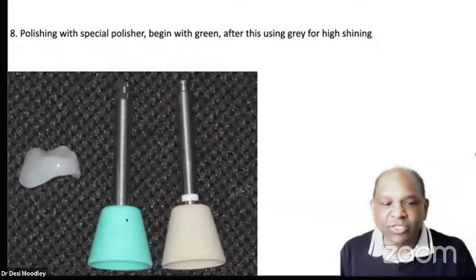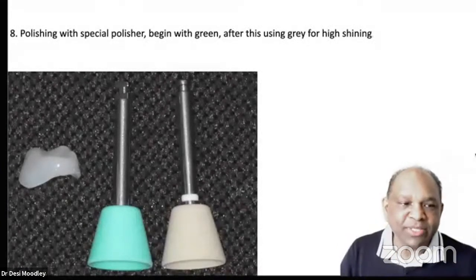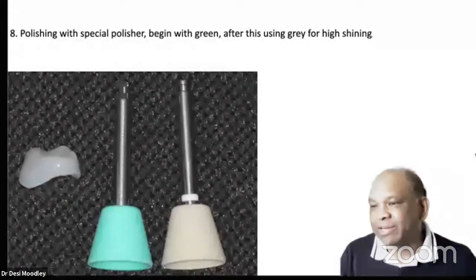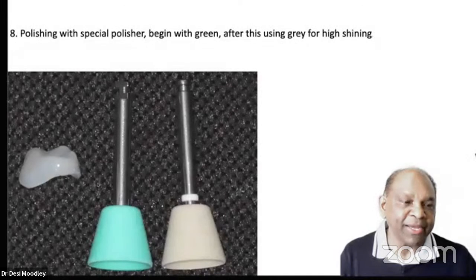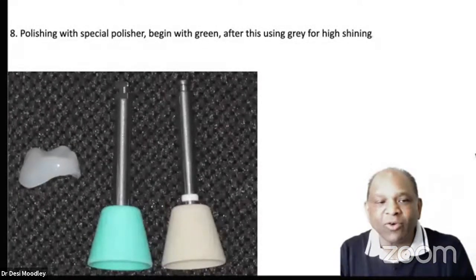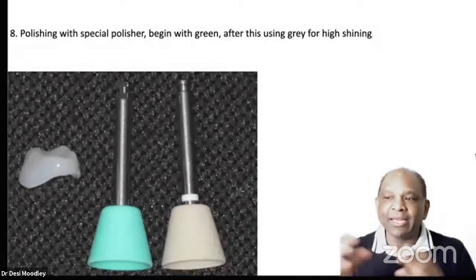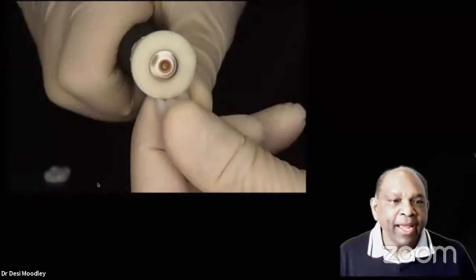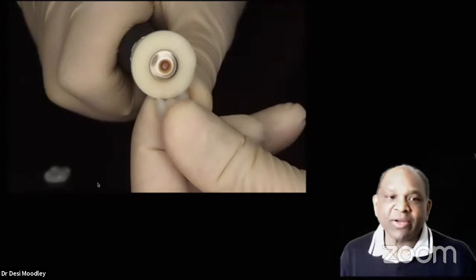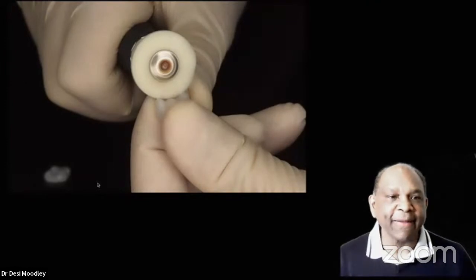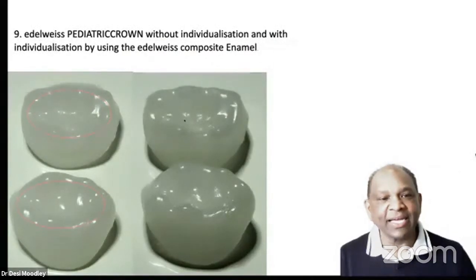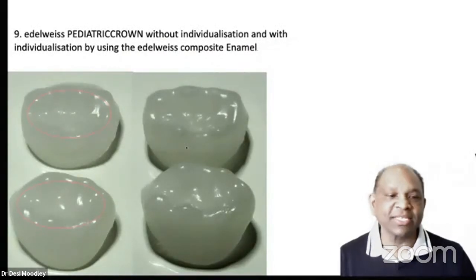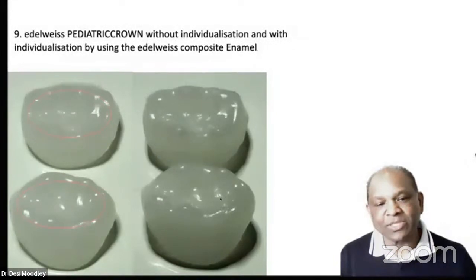And you simply need to use 2 cups, and you will get a final polish that will not be rough to accumulate any plaque. So that's pretty straightforward in terms of closing up a gap or making a crown a little bigger. You can also use one of these polishing wheels to get a better polish in the end. So you've increased the mesiodistal length by simply adding more composite on either end.